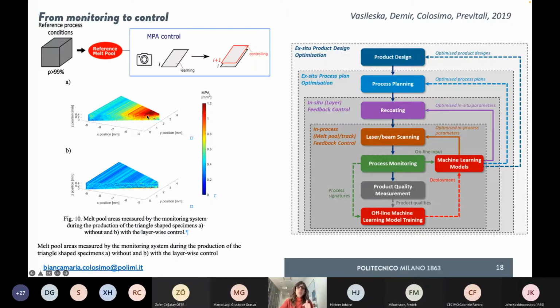What we did is, okay, but can we correct in the next layer the problem? As you know, you are remelting part of the layer you have been printing, or sometimes all the layer that you have been printing. So by, let's say, creating a feedback control action in the next layer, so a layer-wise control, this is going to let you arrive at stability quite soon. And maybe this is also a way of thinking about process optimization done in situ and in line. So you can play with process parameters just by looking at the signature of what you're doing and find the best setting of parameters thanks to this image. And in this case, it was some sort of, let's say, ID of the melt pool.